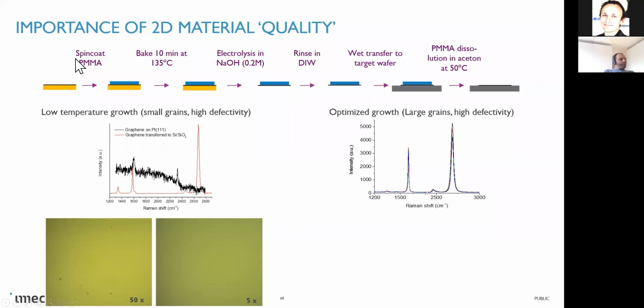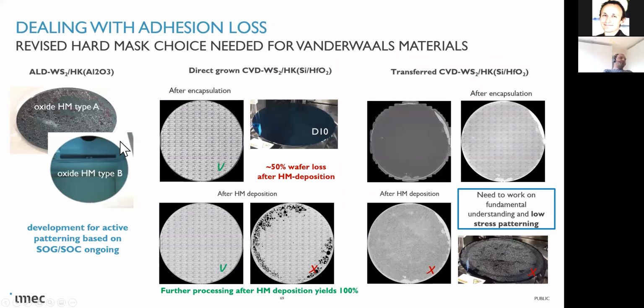And well, it's not fully reflected in this, but what you see here is 300 millimeter wafers where a 2D material has been grown or has been transferred. And as function of the growth or of the top layer or of the stack that is grown on top, we see that we can have very different adhesion behavior. And this is always a concern.